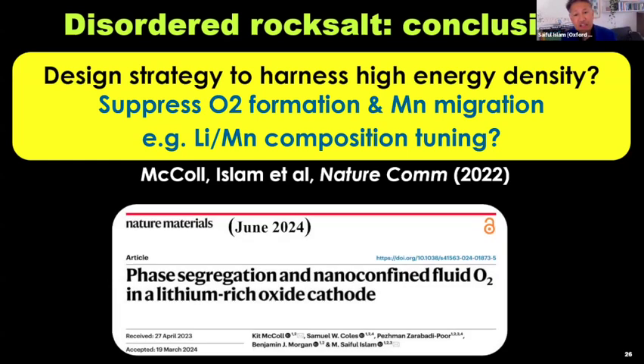We followed up that study to look at lithium-rich layered oxides, and we find similar behavior: molecular O2, or nano-confined fluid molecular O2, within these nanovoids in this lithium-rich layered oxide. And that was published last year in Nature Materials. Because of time, I won't go into details, but if you're interested, have a look at those two papers.